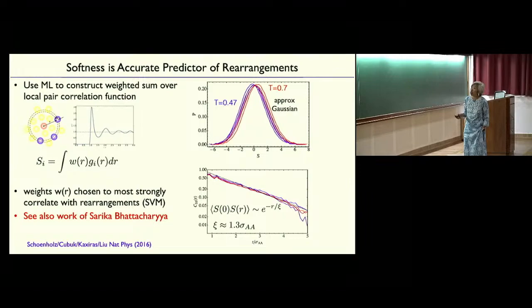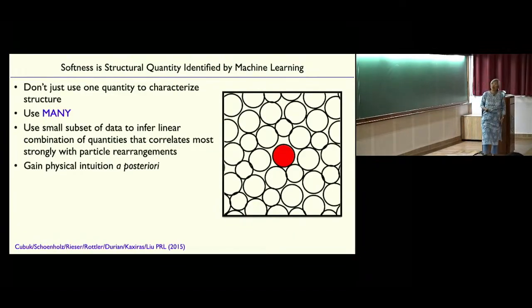So we get this quantity, softness, and it's interesting. It has a roughly Gaussian distribution, as you would expect, because it's the sum of many things. This distribution shifts down as you cool the system, so the particles get less soft: the average softness goes down as you cool. And it's spatially correlated on some length scale, which is of order the particle size. So it has short range spatial correlations that may correspond to what's called the point to set length. It seems to increase even more slowly than the point to set length. All right, so what is the meaning of what we're doing?